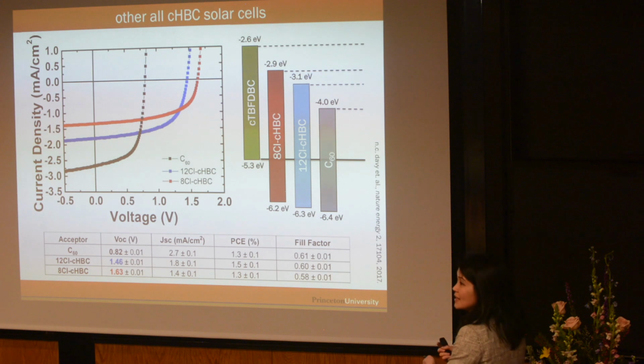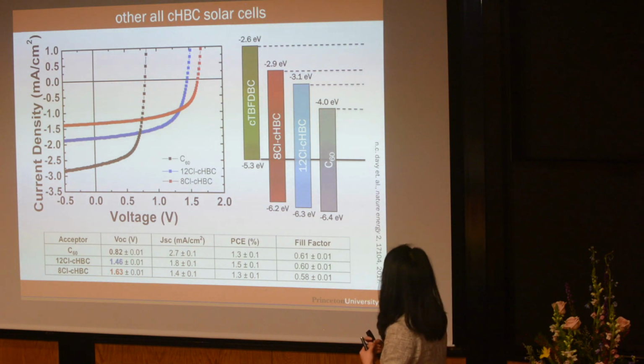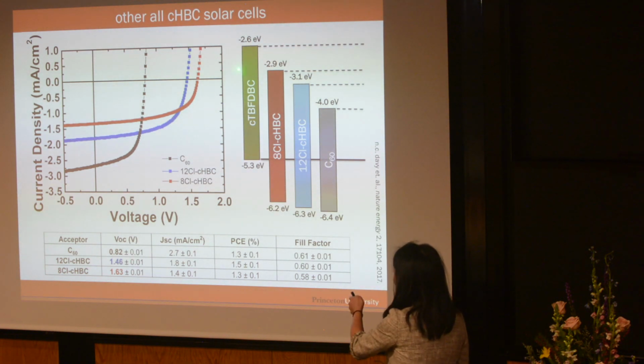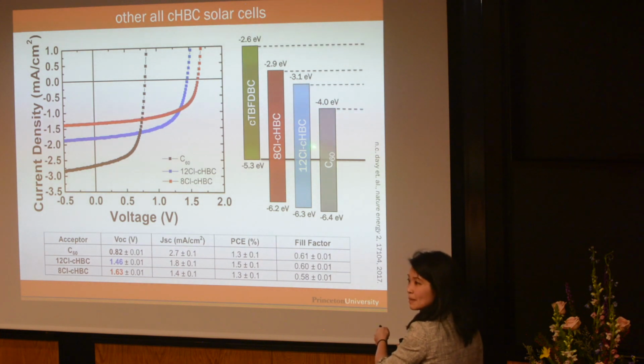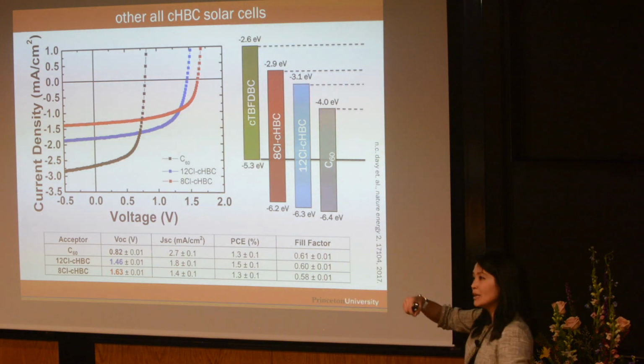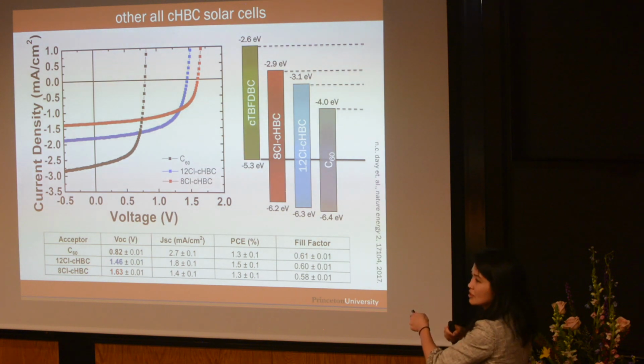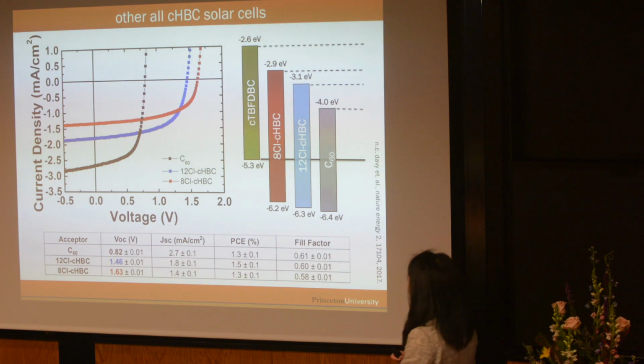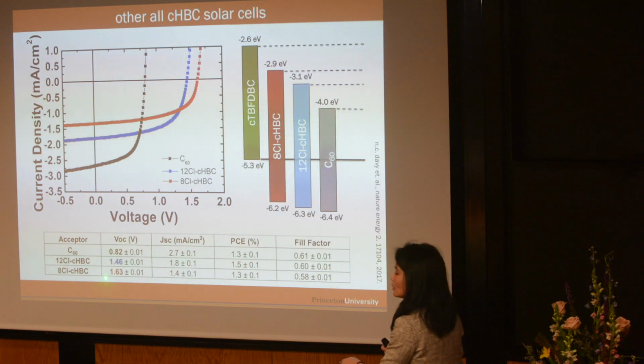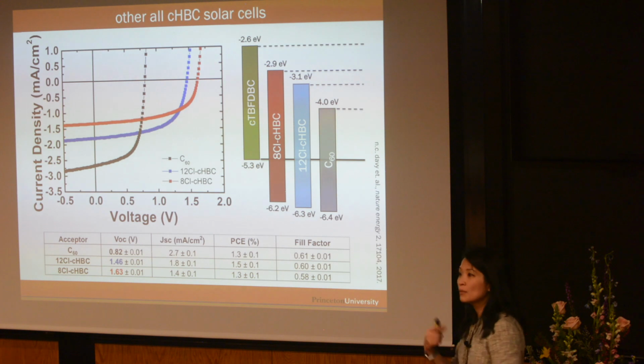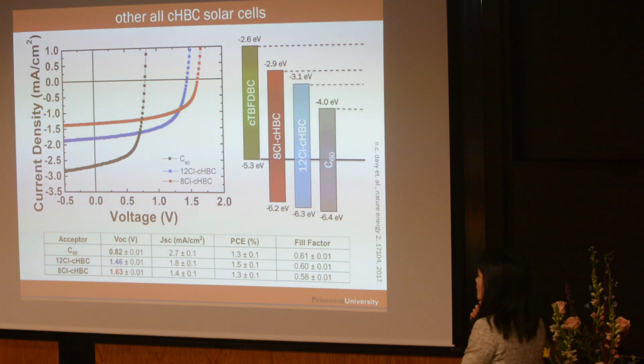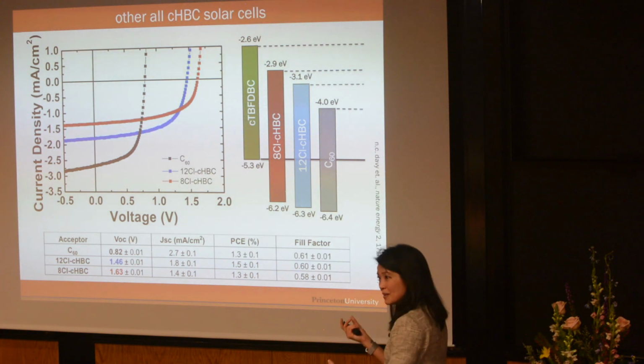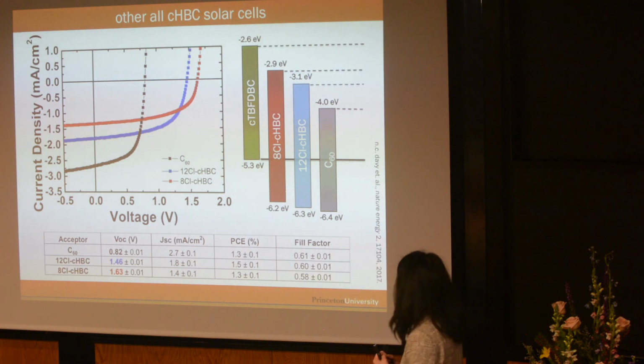We can pair this with other acceptors to just kind of check the behavior and make sure that it's behaving nicely. TBF is our donor. C60 was the acceptor that's colored, right? And as we pull up the LUMO level, we're opening this gap between the HOMO of the donor and the LUMO of the acceptor. And accordingly, you see that the open circuit voltage increases. We go from 0.8 with C60 to 1.5 to 1.6 with 8Cl, and we're approaching 2 today. The currents are small, but that's to be expected because we're throwing away 93% of the photons.